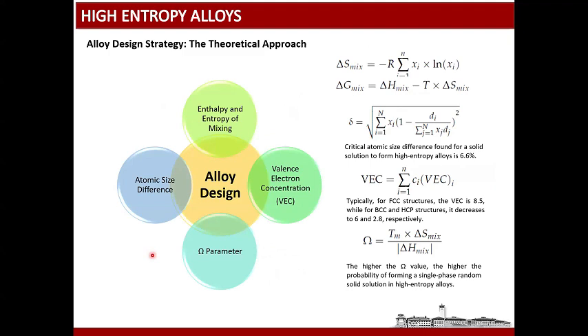In order to design a high entropy alloy, there are different approaches, like theoretical approaches. We can use the high entropy of mixing. As the number of metallic atoms increases in the structure, the entropy of mixing increases. So the configurational entropy increases, and that lowers the Gibbs free energy of the mixture, especially at high temperatures. Another important factor is the atomic size difference. The critical atomic size difference in order to form a high entropy alloy is around 6.6%, and it is calculated by using the different atomic sizes of these elements introduced into the alloy structure.